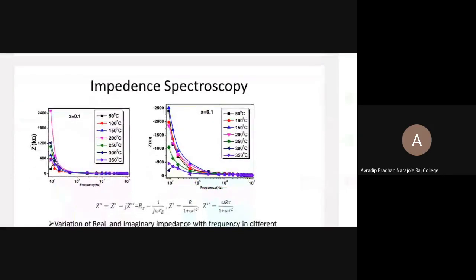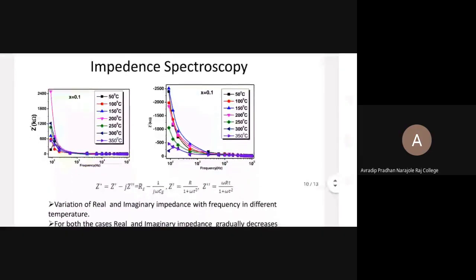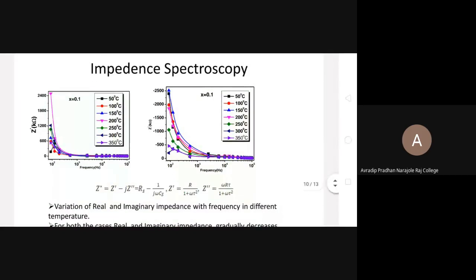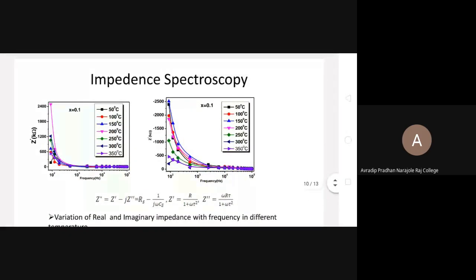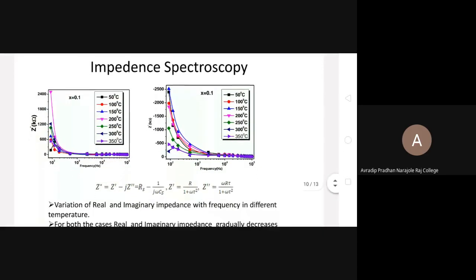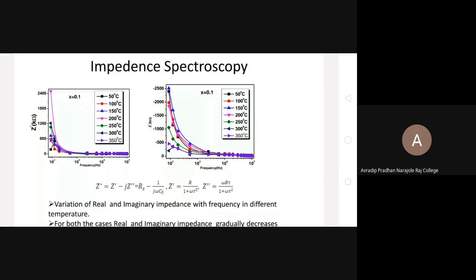And the main thing is the complex impedance spectroscopy of this material. The real part of impedance and conductance is important to study the conductive and resistive properties of this material. Whereas the imaginary part, which is shown in the right side image, is suitable for the relaxation process.